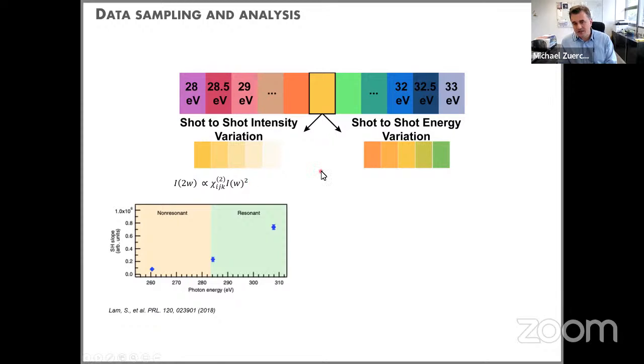So then when we joined these type of experiments, what we then realized as well, it's not just the amplitude fluctuation, but what I just showed as well is we also have photon energy variation. So actually the FEL fluctuates in 2 dimensions, right? It fluctuates in photon energy and amplitude. So what you can actually do, if you collect even more statistics, you can now go and sub-bin each shot by its central energy and then by its amplitude. And if you collect much, much more laser shots, you actually can use that to subsample your spectrum.